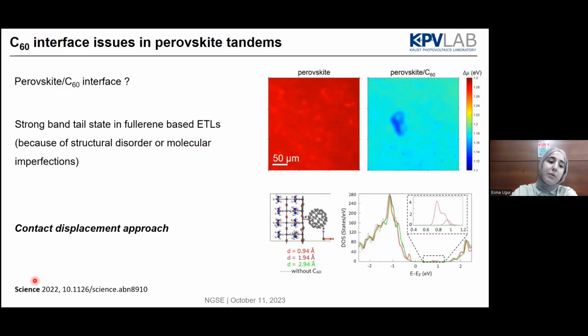Last year, we published a paper that shows that when you put a distance between the C60 and perovskite, you are basically reducing the formation of these density of states within the bandgap. So we call it a contact displacement approach. I think most people in the perovskite tandem field are aware that we need to really passivate that interface or put, let's say, lithium fluoride, magnesium fluoride, different metal fluorides. They are working quite well to make this contact displacement.